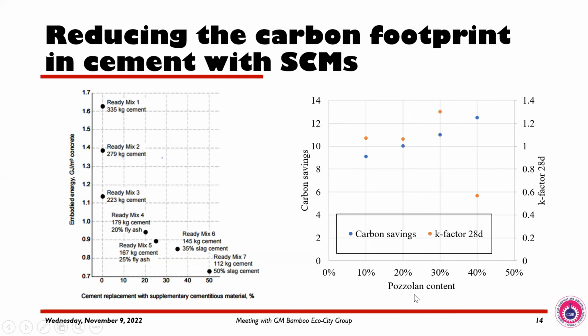So I did efficiency factor and carbon savings when I replaced cement with pozzolans between 0 and 50%. Now, look at something. The blue dots are showing carbon savings. So, of course, when I replace cement with the pozzolana, I'm having a high saving in carbon. You know, as it goes to 40%, you see that it keeps on increasing.